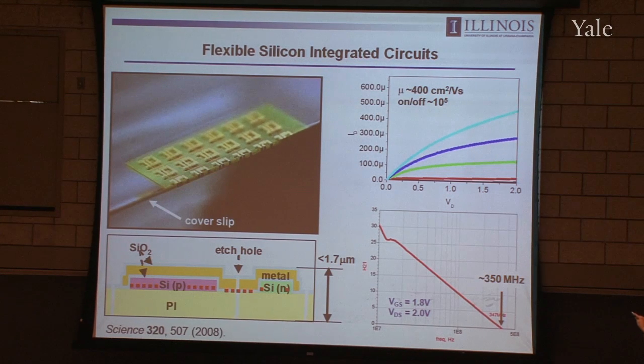So if you look at the intrinsic mobility, it's about the same as what we see in a comparably designed device on a silicon wafer. On-off ratio, the contrast in switching, is very good. You can achieve very high frequency operation even with very coarse channel dimensions because of this very good intrinsic charge transport property of monocrystalline silicon created in this way. So that's a good step towards biointegration, but it's not where you need to go.